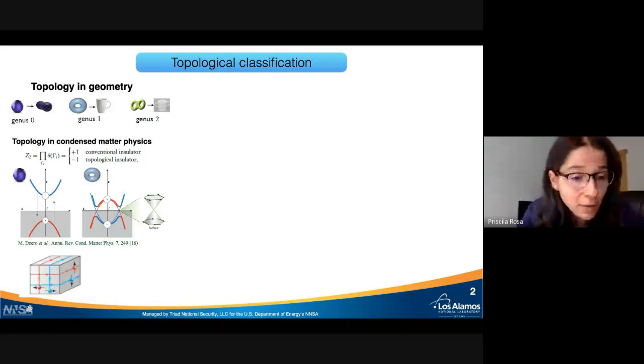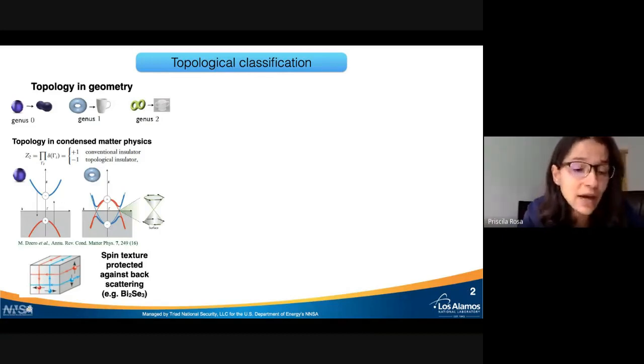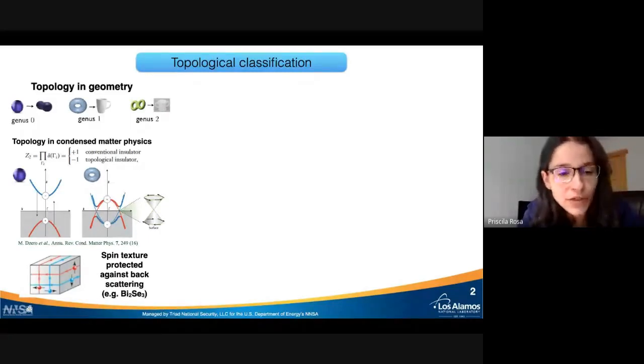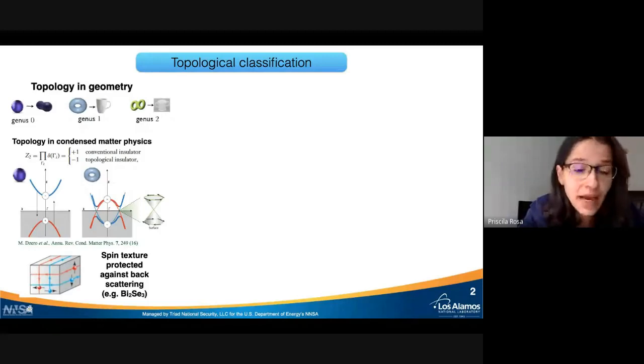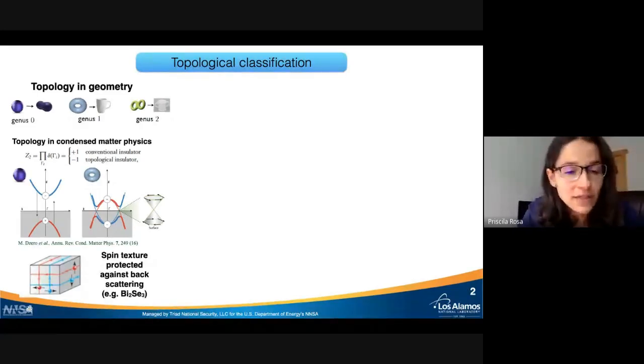And in this sense, we have here a schematic of a topological insulator that has surface states. These surface states have a very important property, which is that they have a spin texture that is protected against backscattering. So if we have impurities or small perturbations of this material, those surface states won't disappear. You may be familiar with examples like bismuth selenide. Why are people interested in this? Well, first, the surface states are supposed to be dissipationless or near dissipationless because they are, again, protected surface states.